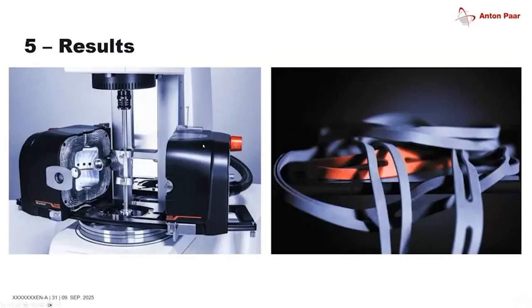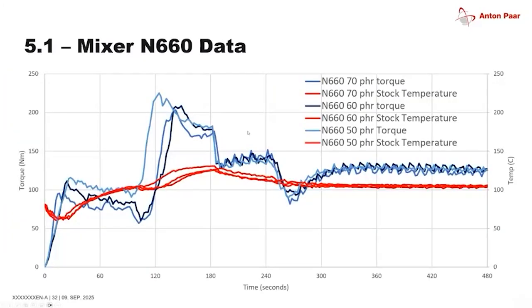Yeah, some of the results. Here we go. So the mixer data. This is everything from the middle of the road, the N660. Remember, we had this middle of the road structured carbon black in 70, 60, and 50 PHR. You always see everything bluish color is torque, everything reddish color is temperature. So we see here that the lightest blue is the one where we are slightly at the highest torque. The other ones are fairly identical.